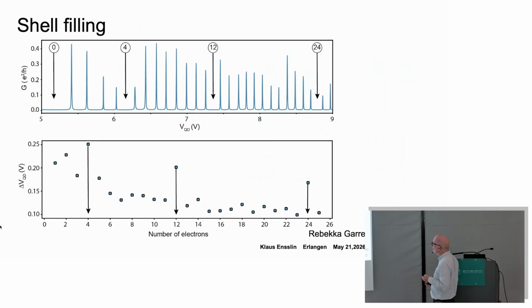Okay, now let's have a closer look at how we fill in electrons in the system. And I show you here a series of conductance resonances. The gate voltage here is just the voltage on the center gate, and you can think of it as being proportional to the energy scale in your zero-dimensional system. So the energy difference between neighboring peaks is basically the energy it costs you to add an additional electron to your system. On the bottom plot, I'm showing you the difference between neighboring peaks, and you see we have to pay a lot of energy for electron number 4, for electron number 12, and for electron number 24.